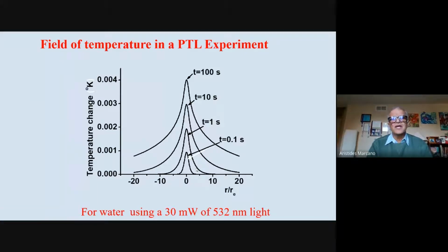So you will grow in amplitude, and you say, what happens if I just keep the laser on forever? So you're going to just burn your sample, no? You're going to evaporate that sample somehow. But anyway, you just keep it in such a way you don't change much the temperature. So in this calculation, I just did it for estimating that I have a laser of 30 milliwatts, and I use a green light, 532 nanometers, and using water, just a couple of millimeters of water, and they produce that small change in the temperature. As you can see, it's similar to the change that one single atom produces in 1 microliter of water.